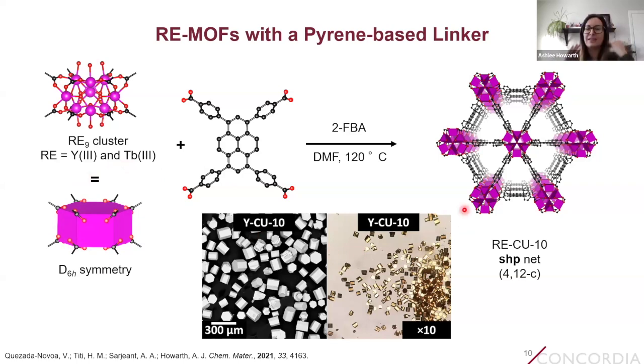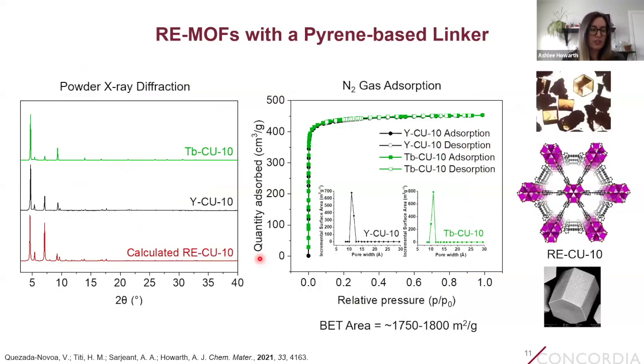And Victor was able to make these really large and beautiful single crystals of this material, so we could determine the structure using single crystal X-ray diffraction. And you can see their nice hexagonal morphology here under an optical as well as scanning electron microscope. So in addition to those single crystals, Victor can also make this material in bulk as a microcrystalline powder. And so here we can see the powder X-ray diffraction patterns showing that for yttrium and terbium CU10, the MOFs are crystalline and phase pure.